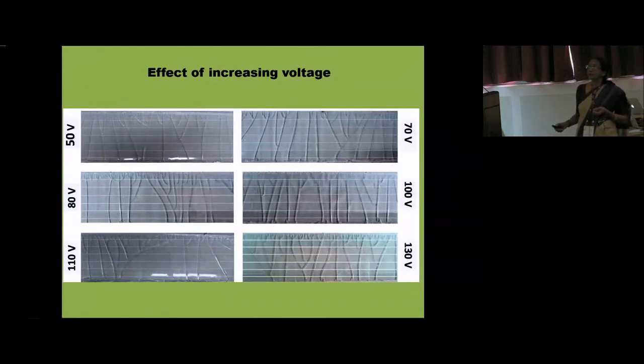This is what happens if we increase the voltage. For 50 volts, this is the pattern, 70, 80, and so on. We can go up to 130. Sometimes there is some statistical effect, so the pattern doesn't look exactly as we expect. But in general, if you compare these two, you can see that as the voltage increases, the number of cracks is increasing greatly. This is a more dense forest with a larger number of trees, and the trees have more branches.